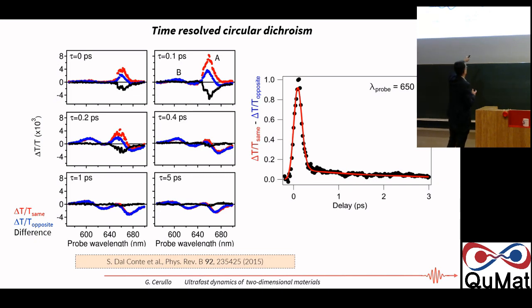And again, if we integrate these spectra, the difference of these spectra, we get a signal that has a very fast decay on the order of 100 femtoseconds and a slower decay of a few picoseconds, which is very similar to the previous result.